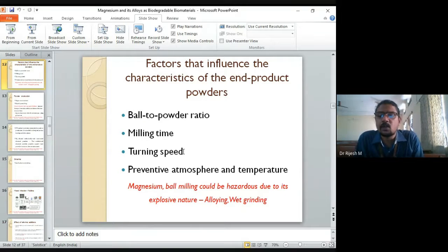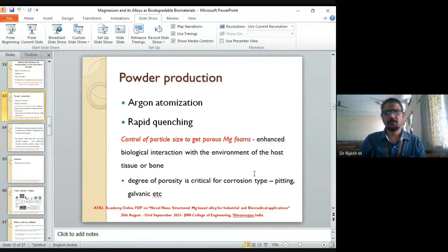The second way is to control the temperature. Controlling the temperature is possible only when you're grinding it in wet conditions. You are using some chemical in liquid form which is not reactive with the powders. The liquid is just to extract heat, making it a wet grinding process where you do not have a very high temperature, so that it does not become explosive or weld. So that is one way of producing powder.